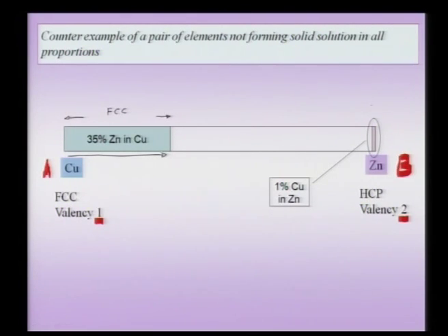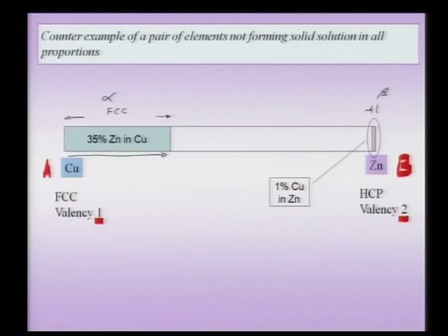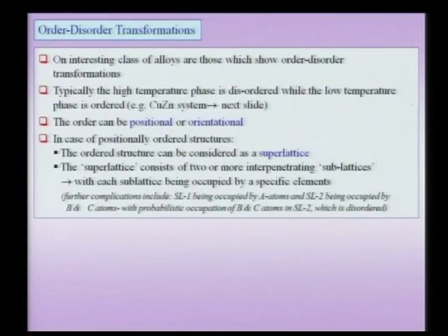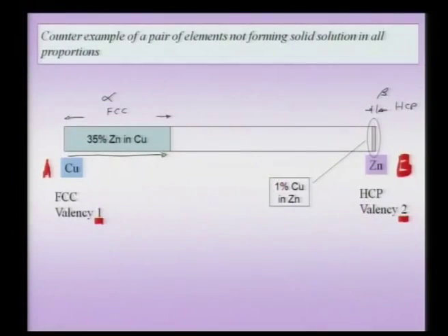On the other hand, using my normal terminology, I could call these solid solutions alpha and these solid solutions beta, and when I use alpha and beta, I mean they are disordered solid solutions. In this region, wherein I find beta, obviously you will have an HCP crystal, wherein in the zinc crystal structure I would slowly replace some of the atoms with copper. So, this is my copper zinc system. We will also later discuss some other interesting crystal structures from this very same copper zinc system.